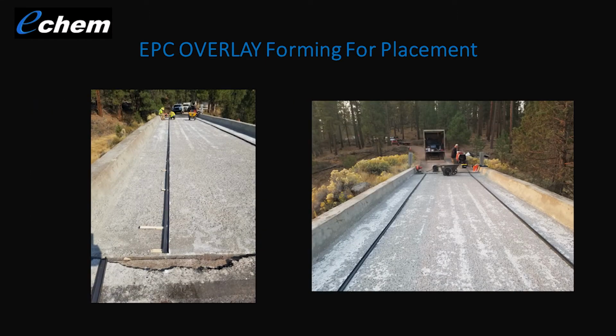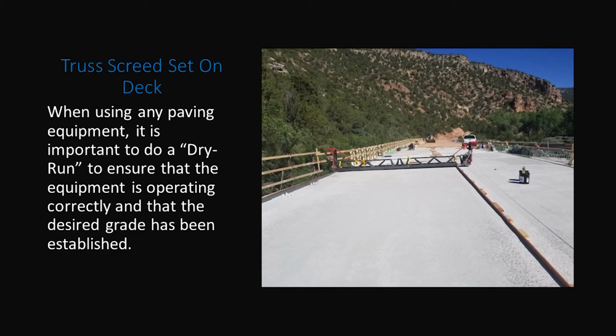A couple more pictures. The Hemis was actually a really nice location. But it was cold in the mornings because we had that high elevation, about 8,500 feet at this point in the valley. This picture was a project we did in Oregon. It was a fire service bridge that they tried to put a couple of different overlay systems on. They weren't able to complete it just because of the location. It was a very remote location, and we were able to get the EPC in there and get that project done. We got the truss screed set on the deck.